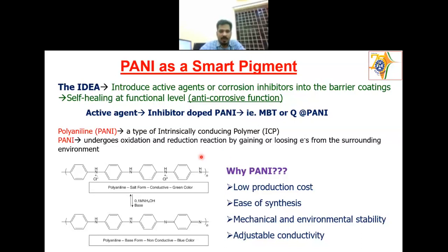So why PANI? When you synthesize, we have two forms actually, salt form and base form. Generally, we will get the salt form only. If you're using HCl as the acid, you get the chloride anion. Instead, if you use phosphoric acid in the synthesis, you will get the phosphate ion here. So PANI phosphate you can make, PANI chloride you can make, and later people are using some organic acids also. Based on what kind of surfactants or dopant you are using, you can dope that on the nitrogen here. When you do a base treatment with NaOH, the dopant completely goes away and you get the base form. The base is non-conductive, while this is the conductive form. It will generally be green in color, and the base form is blue in color if it is non-conductive.